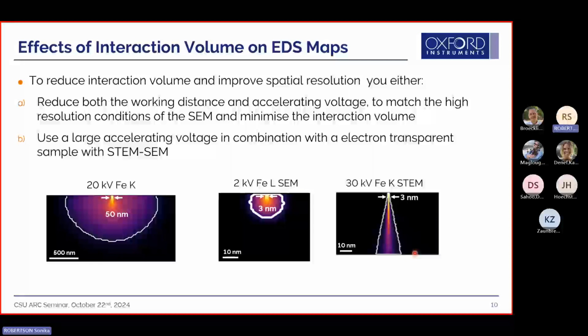Well, that's 30 kV. So next few slides, I will show you results on low kV and then some examples on STEM, because when low kV is not enough, I forgot to talk to you about if you go for dual beam analysis, but being able to get lamella and doing the analysis on the same SEM with the EDS detector will allow you to further push the resolution limits for X-ray mapping.